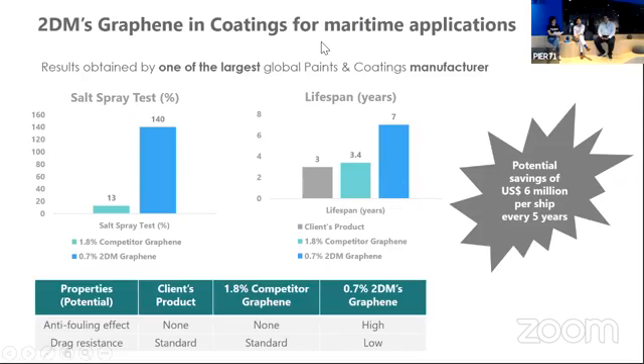For example, some ships have heat exchangers, and if you coat with a normal coating, normally you lose efficiency of the heat exchanger. If you use a graphene coating, you get the same level of protection from corrosion, or maybe even better, and you don't lose efficiency because graphene can make the thermal exchange even faster. And also there is a very important area that is defense. If we move along from coatings to composites, to ballistic composites for defense application, I think who can describe a little bit better? Thank you.